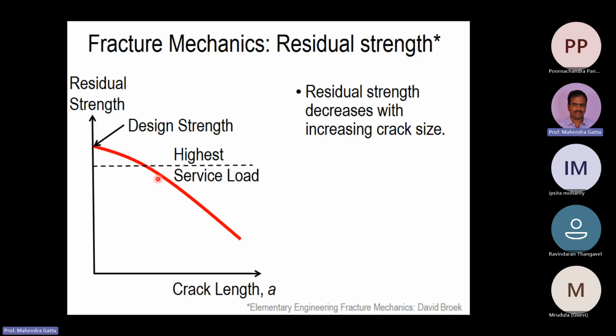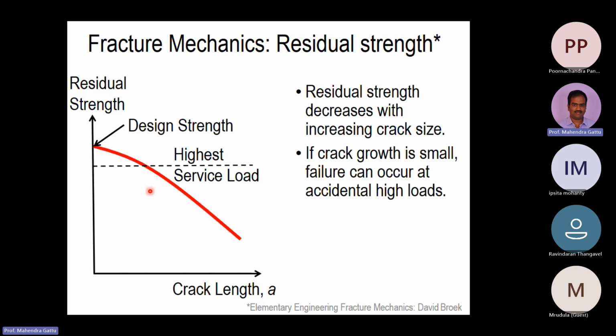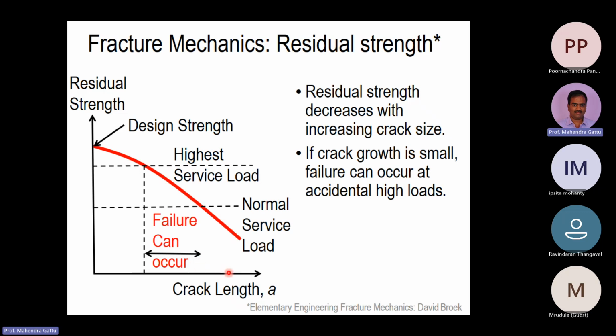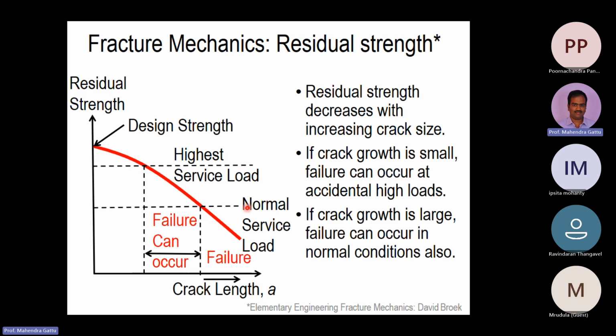And usually, if the crack length size is say less than this, between here to here, then for the design service load, the structure is safe. But if the crack length exceeds this value, then for the applied service load, it might fail. Okay. And if suppose the crack length is very large, so if you are in this region, then the material might fail even for normal service loads. So if the crack length is very large, then the material can fail even for normal service load because the residual strength drops with the increase in crack length.